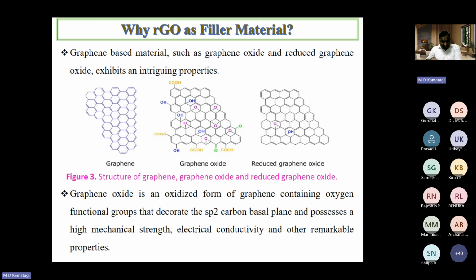Pure graphene oxide is an insulating material, whereas the reduced graphene oxide regains properties similar to that of graphene, which exhibits a higher electrical conductivity, improved mechanical strength, and enhanced thermal stability. There are several methods to make reduced graphene oxide. To name a few: chemical reduction, using reducing agents; thermal reduction, heating the graphene oxide to a very high temperature to remove oxygen functionalities; electrochemical reduction, photothermal, and laser reduction. We have used a chemical reaction method to reduce graphene oxide into reduced graphene oxide.